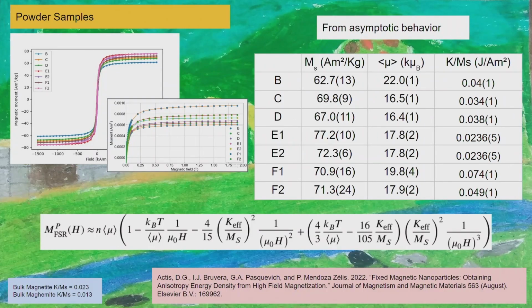So from powder samples, we work with the asymptotic behavior, where a few months ago we made some study of how we can obtain information about the mean magnetic moment and the magnetic saturation. That is very easy, because if you know the sample and you measure the magnetic saturation, divided by the mass, it gives you the saturation magnetization, and the relation between the effective magnetic anisotropy and the saturation magnetization. All this information can be obtained from fitting the asymptotic behavior. So we characterize that.